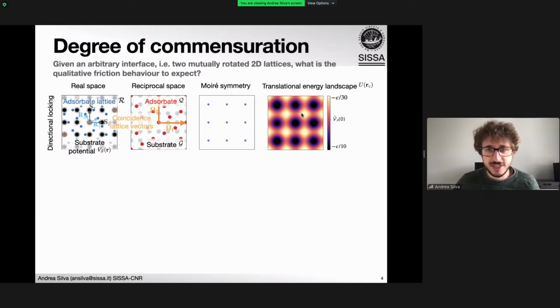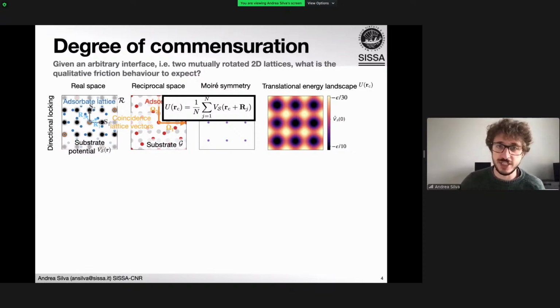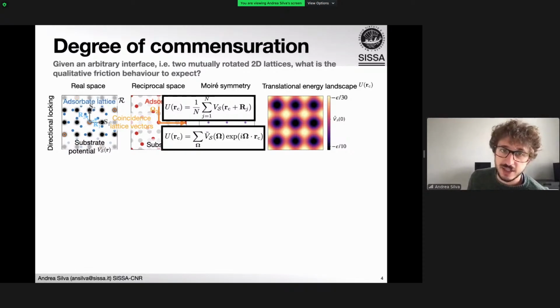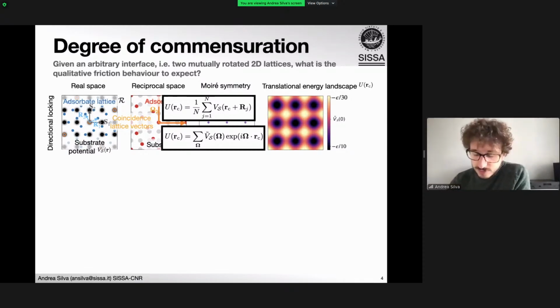And just to get a bit more detail, this can be computed numerically, which is usually done in codes by really summing over the atoms building up the interface, or we did it by using a Fourier transform of the potential, which is an exact match in this periodic infinite system. So this is the case of directional locking, where friction is high and you expect stick slip.